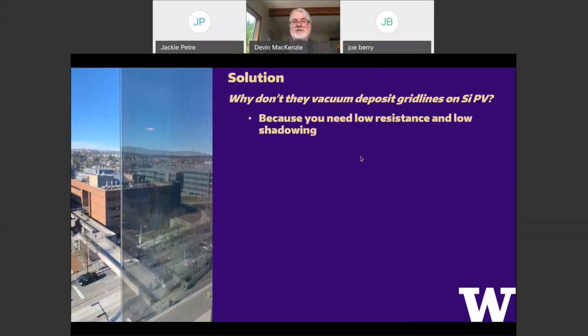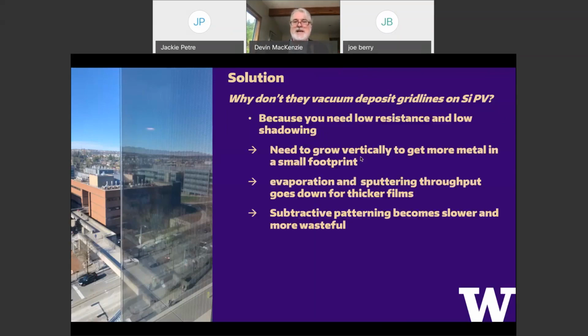Well, you can think about what you do in silicon. They don't use vacuum. They don't vacuum deposit grid lines on silicon PV, because we need low resistance and low shadowing, and that's hard to do. We need to grow vertically to get more metal in a small footprint. If you want low resistance and low shadowing, you need to go vertical, not laterally. And of course, vacuum depositing is also subtractive. We want 90+% transmission, so if we throw down a bunch of gold, we're going to etch away 90+% of it, which is very subtractive, very wasteful.